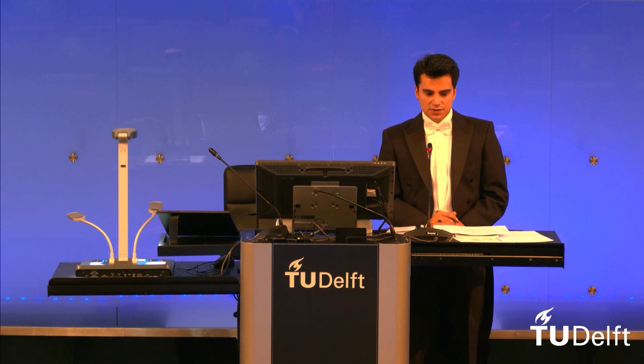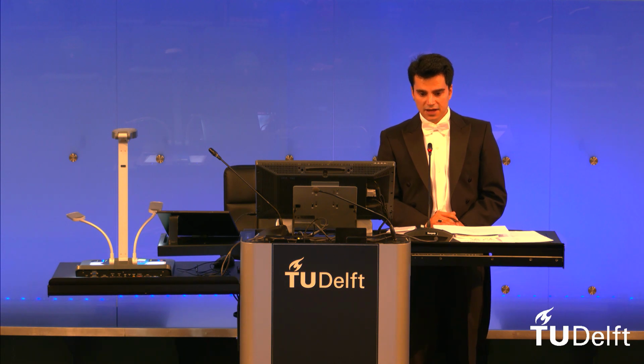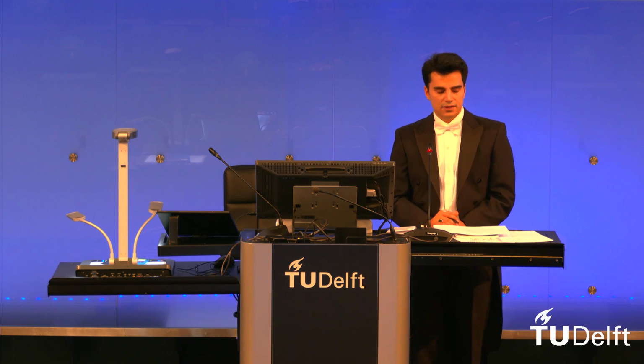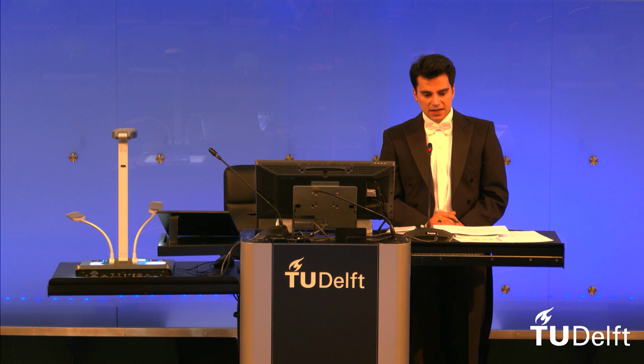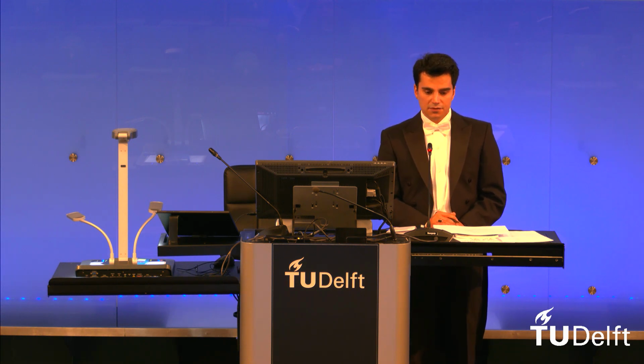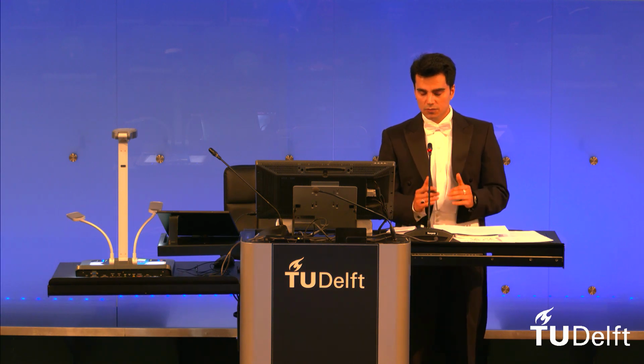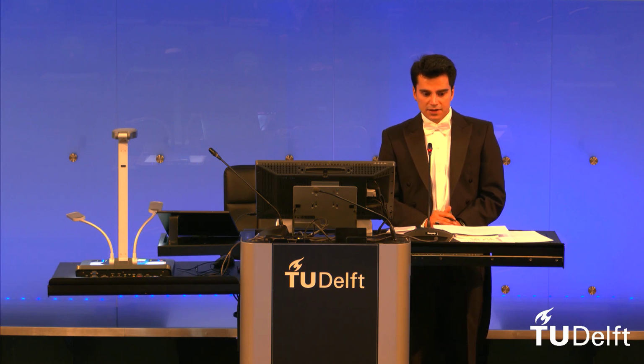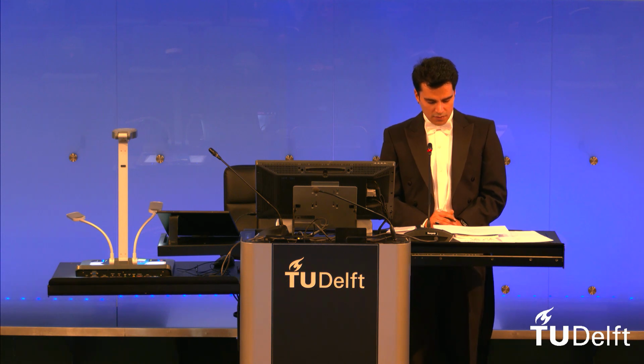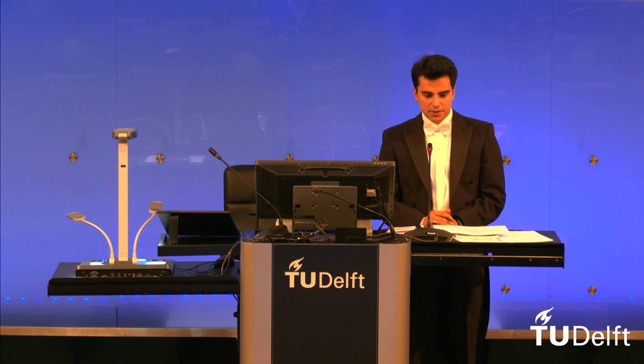According to the examinations that this PhD candidate did, we could confirm that the microstructure is quite similar to martensite. Therefore, he could conclude that the nature of the samples studied in this research has been martensitic. And of course, I reported that in the literature, the second type could also be the case. But the problem is that we never know if, in reality, the white etching layer has faded away, has been worn out during normal rolling contact. So it is a bit controversial to confirm whether you have samples that may not have any reference of white etching layer on them. But having said that, there are many researchers that claim that this also could be the case.